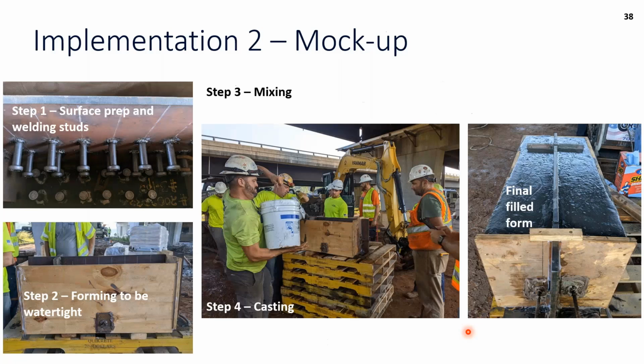Moving on to our mock-up, since we were only doing a partial height repair, you can see this mock-up is a lot smaller than the other that we had used. One of the things that we did see with the weathering steel is that getting that nice weld around the stud was more challenging. So it took more tweaking of the gun and some of the settings, and the surface cleaning, I'd say, is even more paramount when working with the weathering steel.